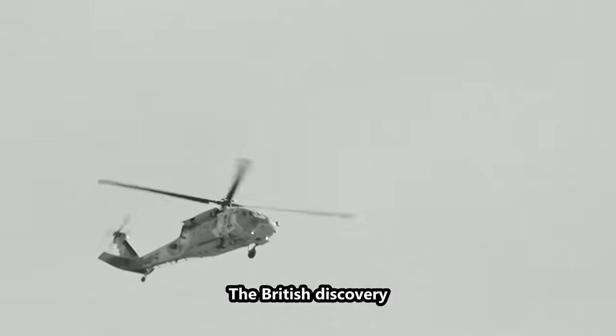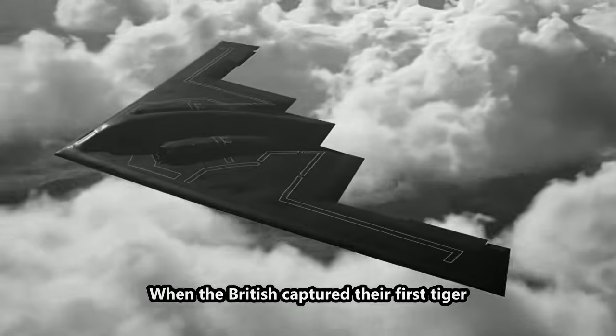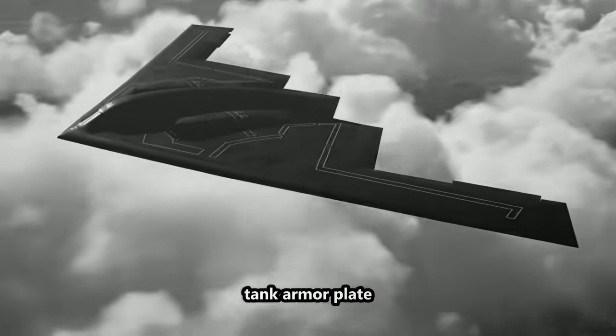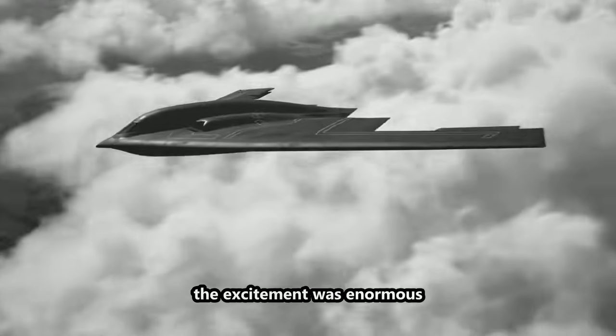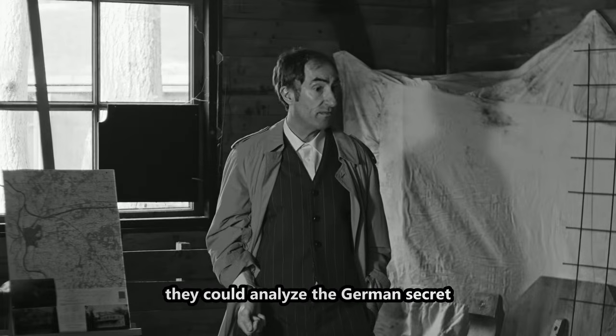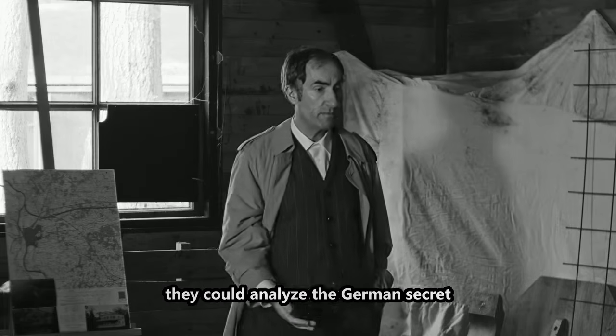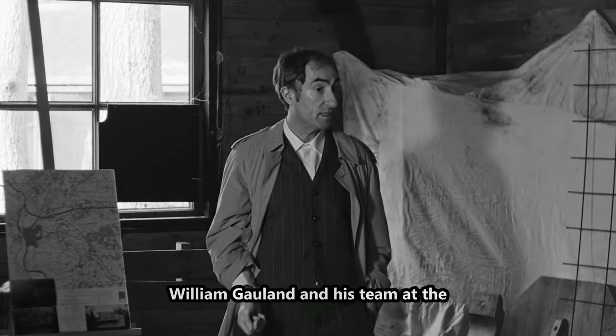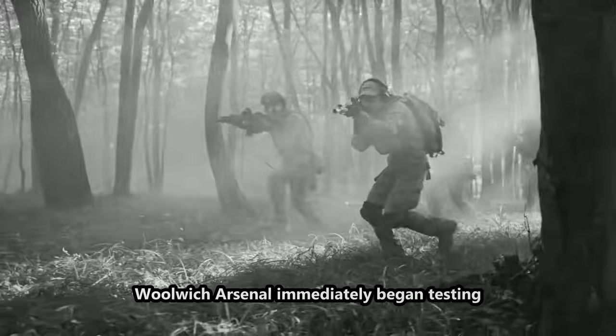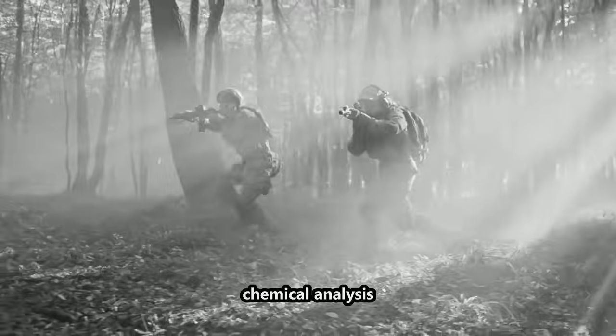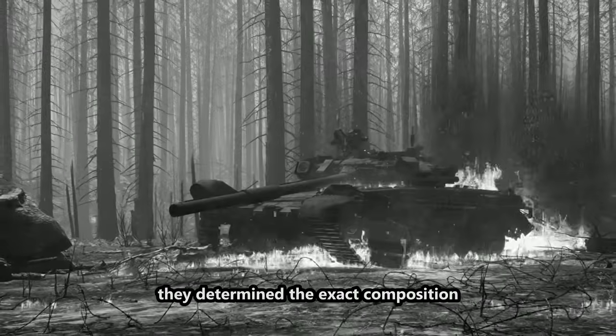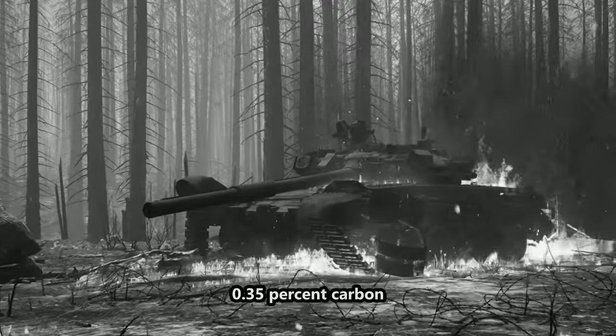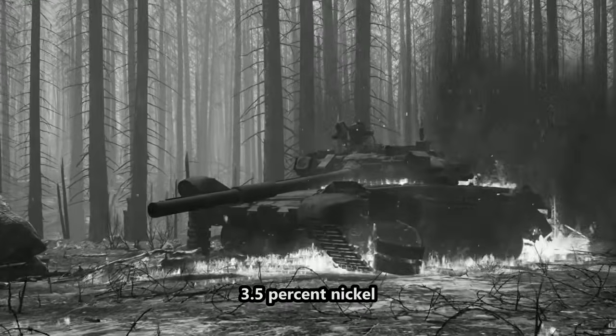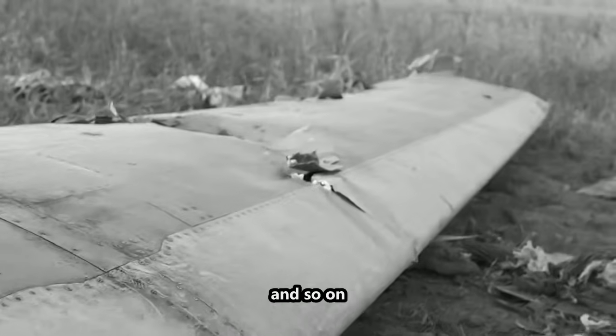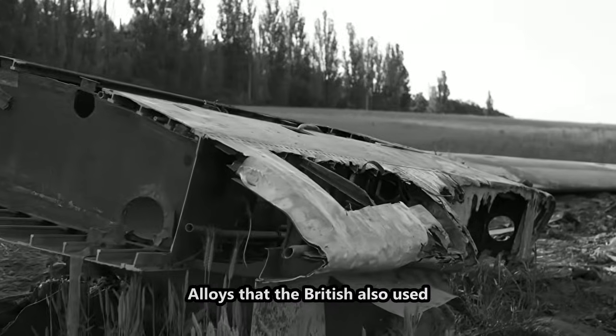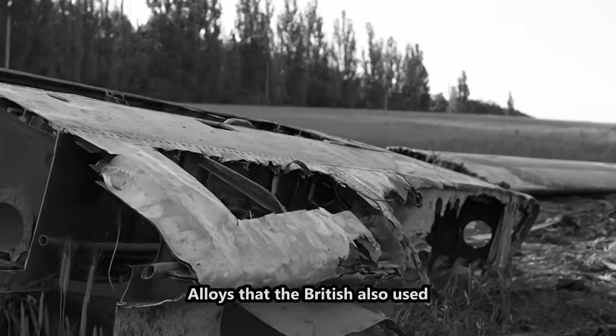The British discovery, a steel that couldn't be explained. When the British captured their first Tiger tank armor plate in 1944, the excitement was enormous. Finally, they could analyze the German secret. Dr. William Gowland and his team at the Woolwich Arsenal immediately began testing. First, chemical analysis. They determined the exact composition: 0.35% carbon, 3.5% nickel, 1.5% chromium, and so on. Nothing unusual. Alloys that the British also used.